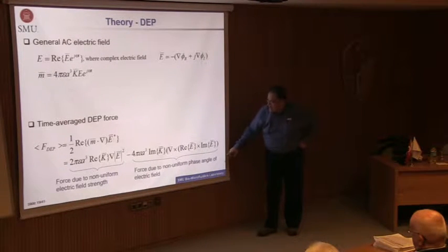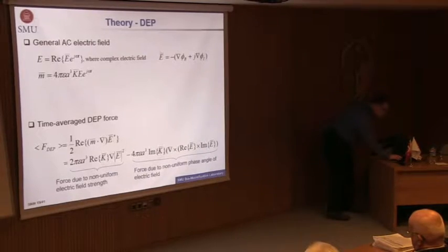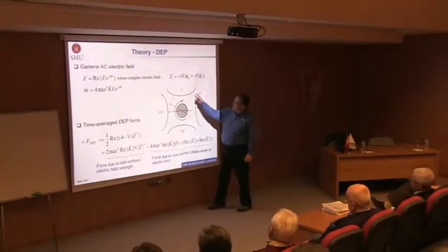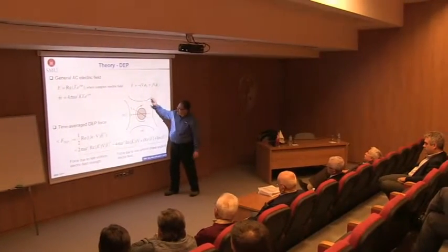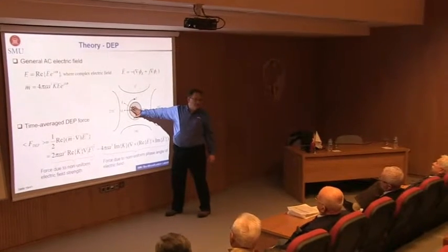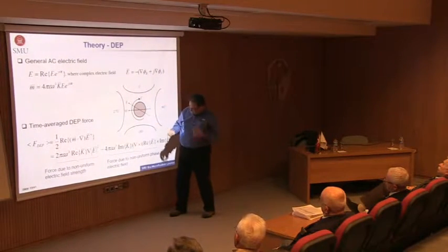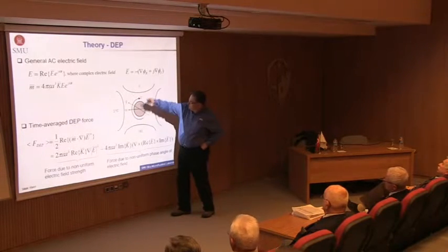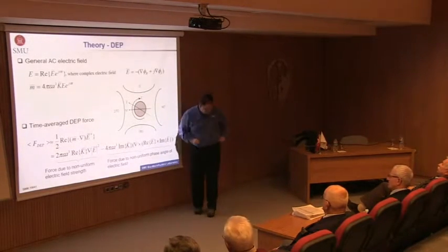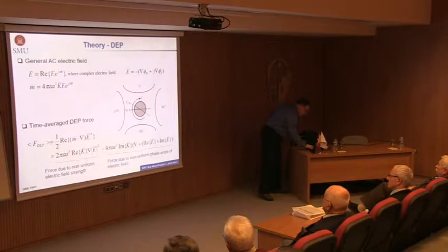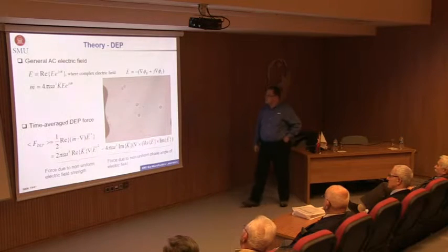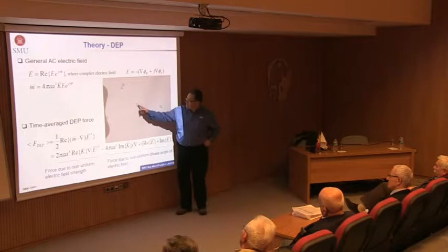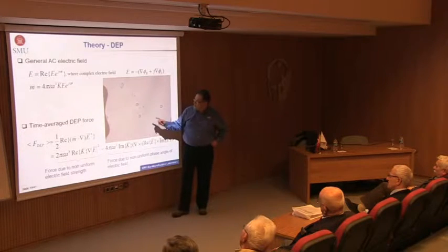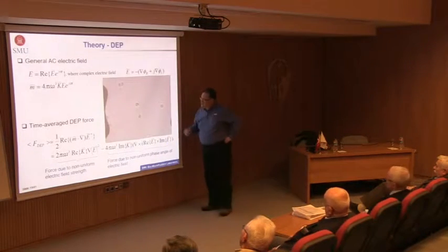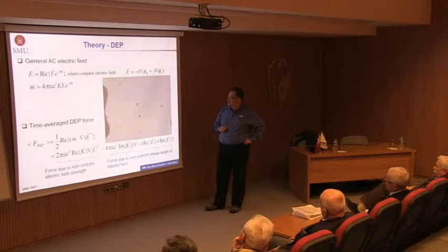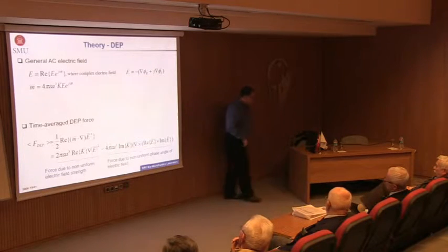The first one is what we emphasize in our studies, but this is basically due to the non-uniform phase angle of the electric field. I would like to demonstrate what happens if I use 4 electrodes, and these are the polarities, and let this turn. As you turn this around, you make sure to turn a particle in between, because the dielectric properties of these particles will react to this turning electric field. This is what happens if you're using cervical cancer cells, HeLa cells. You can see one electrode here, another one there. They're turning at different speeds. The rotation rate is actually an indication of the electric properties of these particles. I did not pursue this any further.